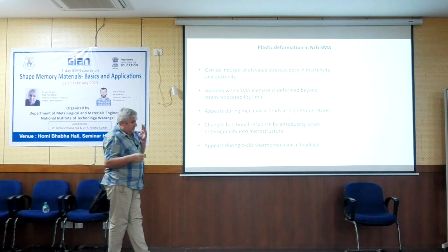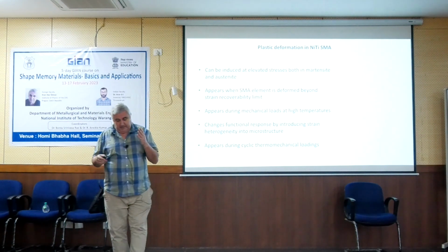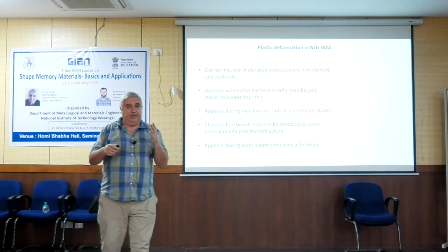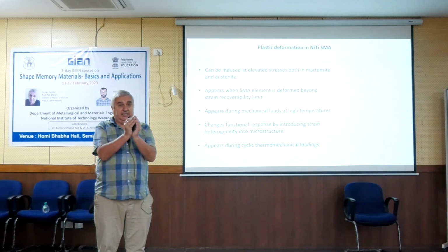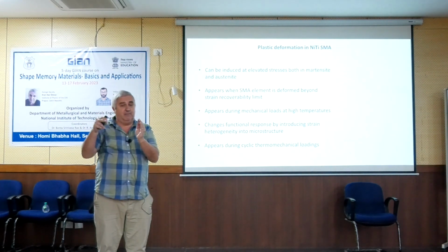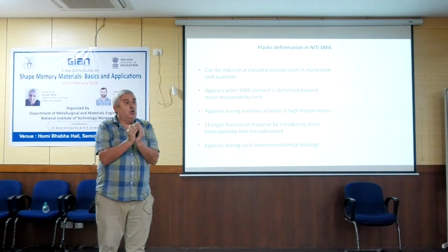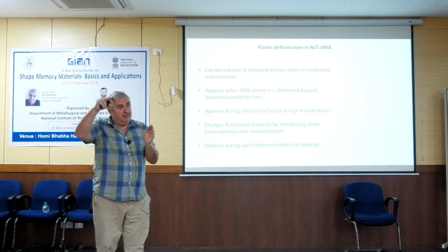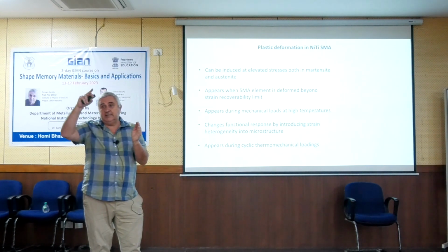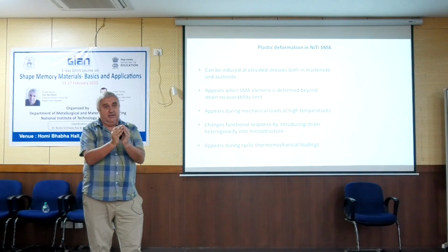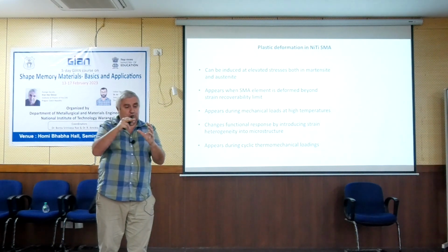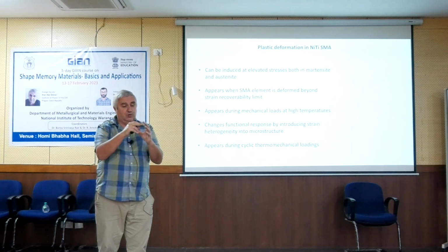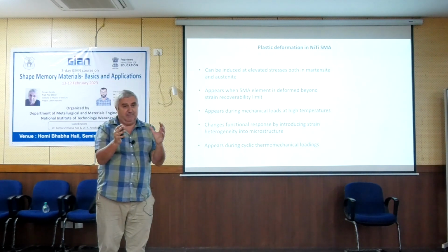And there is another principal point. If I have a shape memory alloy element, and it deforms only by martensitic transformation, I do any kind of thermomechanical closed loop, and if I come to the same point, I am in austenite and there are no defects. I showed in the shape memory effect yesterday, we load in martensite, unload, heat, and there are no defects inside. So these models assume that the shape memory closed-loop cycle will be completely closed, with no unrecovered strain and no defects.